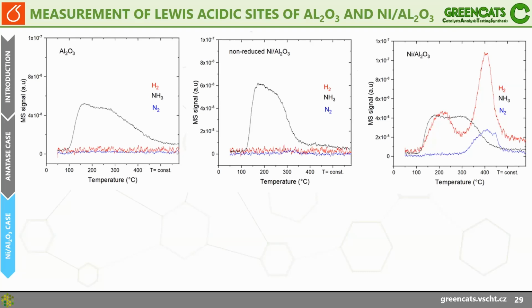The reason for that is that ammonia obviously can adsorb also on the nickel sites that might have, let's say, certain acidic, Lewis acidic character, but it is not desorbing. Rather, at these conditions, it is decomposed into nitrogen and hydrogen. So that is a little bit changing.